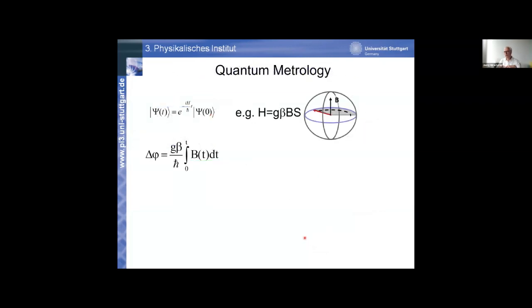In practice, we do these experiments through a time-dependent measurement. That is, essentially, we measure the Larmor precession of the electron spin in the external magnetic field. As you know, the spin wave function, if you have a Hamiltonian you want to measure, is propagated by this Hamiltonian from a starting wave function, which in other words means the electron spin is precessing around the magnetic field with a frequency proportional to the magnetic field. We run our experiment in such a way that we apply microwave pulses, which switch our spin state into an initial spin wave function. And at some point, we apply another microwave field. So this is a classical Rabi oscillation type of experiment where we then stop this evolution.